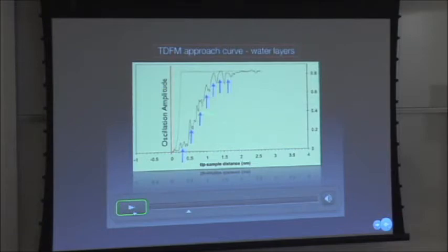Okay, so the first thing, this is the amplitude of oscillation. The probe is oscillating, and we're measuring the amplitude. We're approaching the surface, so here we're at 2 nanometers, and then something starts to happen. The amplitude goes down to about 1 nanometer. But look, there are peaks. There are peaks in this, about 2.5 angstroms apart. First it returns to the same level, and then it starts to go down.